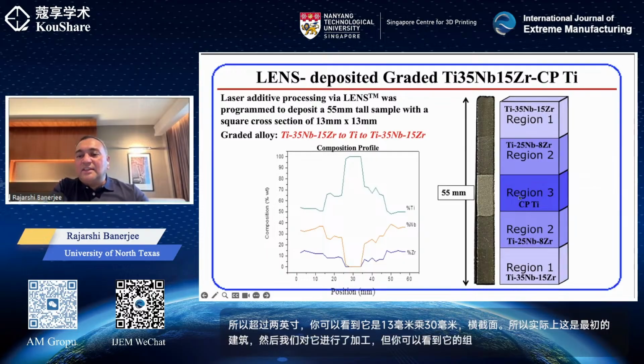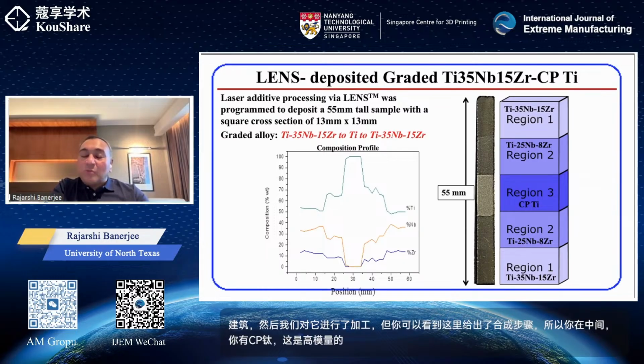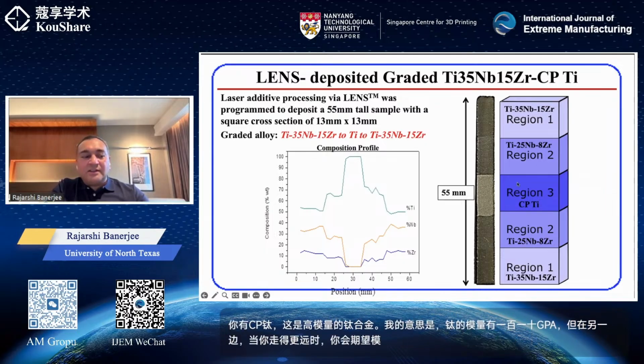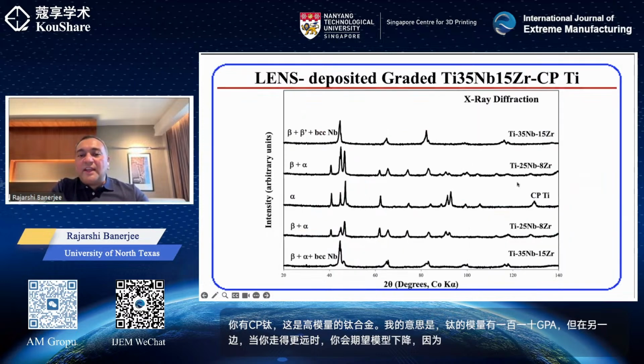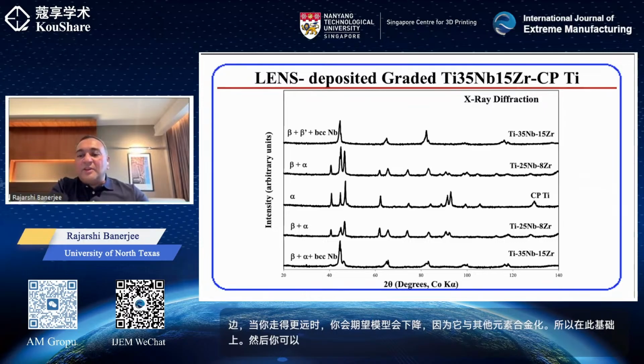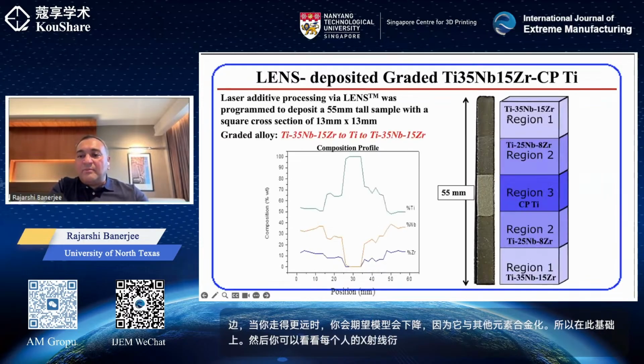So in the center you have CP titanium, which is the high modulus titanium alloy, with a modulus of about 110 GPa. But on the other side, as you go further, you would expect the modulus to go down because of this alloying with other elements. So based on that, you can look at the X-ray diffraction from each of the layers. Here we decided to do 5 macroscopic layers. They're very thick. In a real design, you would like to make them much thinner, but this was just a proof of concept, as I said.